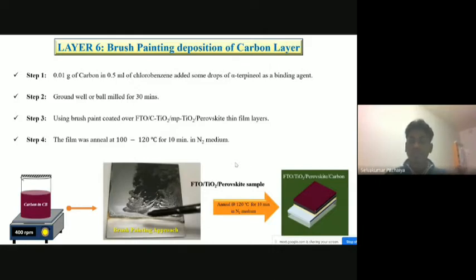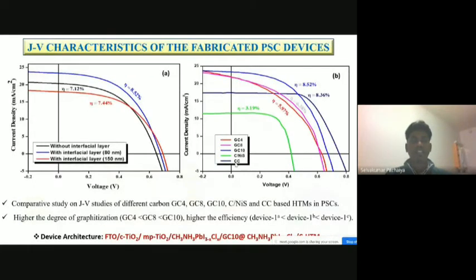Previously you had to optimize spin coating or spray coating deposition, including the solution viscosity, spin rate, annealing temperature and everything. But these brush painting techniques are easy and a novel approach, which we are following. This is the JV characteristic of our work. We also compared it with commercially available carbon paste, which is a high-cost material when you purchase it from commercial industries. Our invasive plant extracted carbon performs competitively, similar to the conventional carbon material.